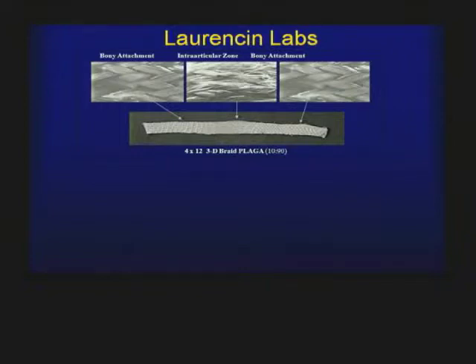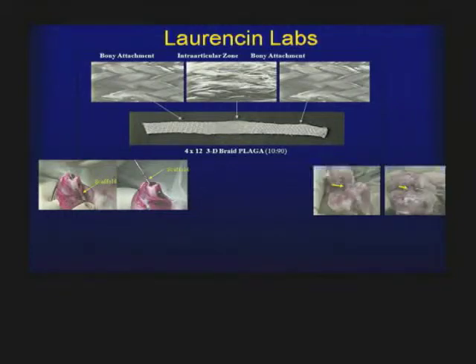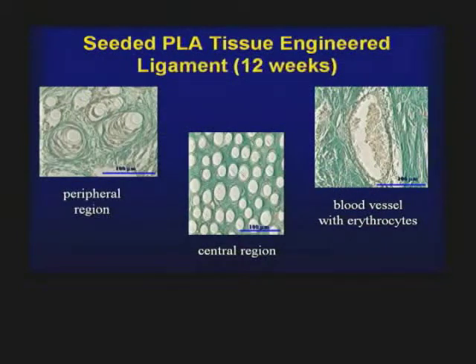We've designed a bone-tendon-bone type of ligament scaffold to regenerate the ACL. We did this by studying the tissue in a hierarchical fashion, mimicking it, and then reproducing the material. We created a model for ACL regeneration in the rabbit, and implanted it. After three months in the rabbit, you have a glistening ACL. Interestingly, during the time the rabbits have the ACL implanted they're moving around very well — difficult to control their motion in terms of physical therapy, but they're moving quite well.